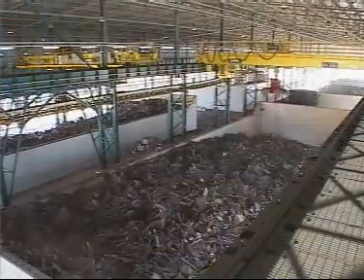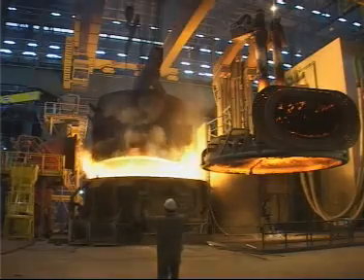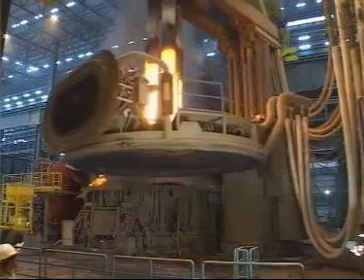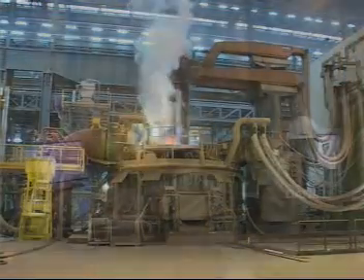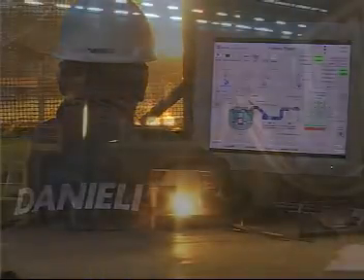The 7,700 millimeter diameter shell furnace is charged with hot briquetted iron, which represents up to 30% of the overall charge. Alternative chemical energy is supplied to the EAF through a compact design module system for oxygen and carbon injection, with the aim of saving energy and reducing conversion costs while increasing EAF productivity up to 198 tons per hour.